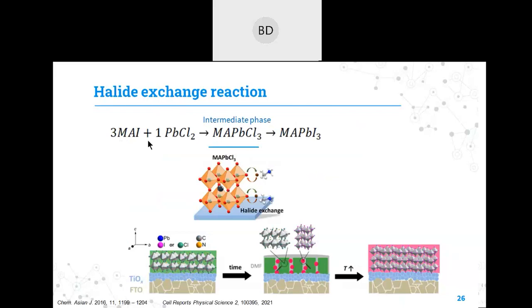So in the lead chloride route, we have used PbCl2 as a precursor. This PbCl2 is not directly making the MAPbI3. First, it makes a MAPbCl3 intermediate phase. This MAPbCl3 has a perfectly cubic structure, and from this MAPbCl3, formation of MAPbI3 happens through a halide exchange reaction. This halide exchange reaction is very slow in process. It takes around 2 to 2.5 hours of temperature annealing at 100 degrees centigrade to form a perfect MAPbI3 structure.